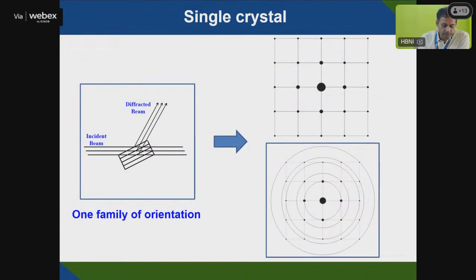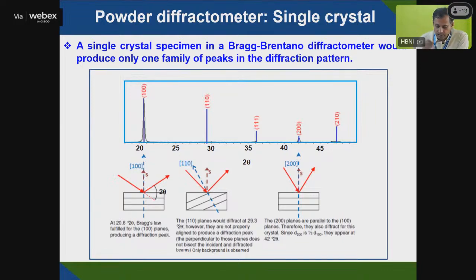Here, this is a single crystal, and all planes are oriented in one direction. So the incident beam is diffracted in one direction. What you will get is a spot pattern instead of multiple beams. I have taken a single crystal specimen here, and this is the oriented plane. If you see here, that is the 100 plane, the incident beam comes in and is diffracted, 2 theta is satisfied, and you are able to see that 100 plane.